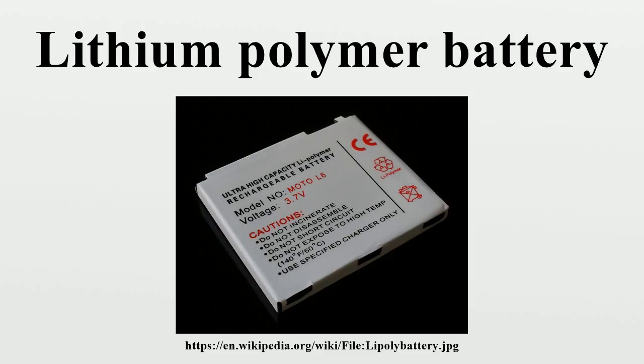However, it has been investigated that moderate pressure on the stack of layers that compose the cell results in increased capacity retention, because the contact between the components is maximized and delamination and deformation is prevented, which is associated with increase of cell impedance and degradation. Applications. LiPo cells provide manufacturers with compelling advantages.